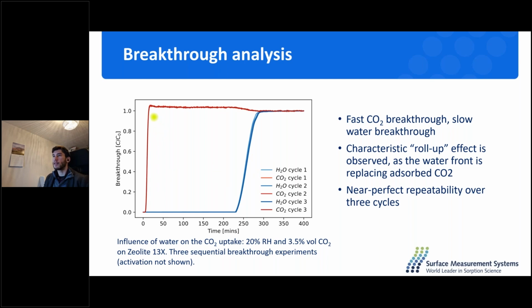And one other thing to note is that when it comes to the concentrations that are measured at the end, the concentration of CO2 seems to go above the initial concentration. So after CO2 breaks through, we seem to have more CO2 at the outlet than we're putting in. This is what is called a roll-up effect. The reason behind this increased concentration at the outlet is that the water that is coming in at the inlet of the column displaces CO2. So it kicks out CO2 from the adsorbed phase. So what is being read at the outlet is the inlet concentration plus the CO2 that is being displaced by the water. And this is why the concentration goes above unity at the outlet while water is being adsorbed. And as water breaks through, it goes back down to the same concentration as the inlet.